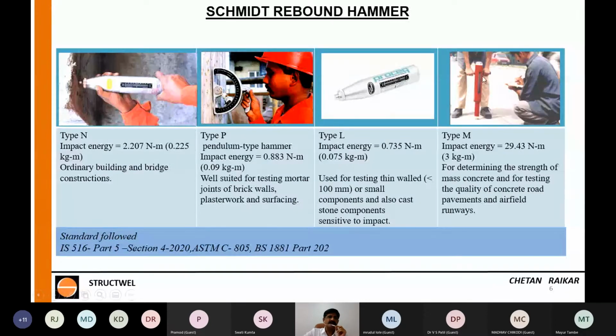This is Schmidt hammer. Schmidt hammer is of different types, you know, M type, that is medium, L is light, P is pendulum type, N is normal. This is generally used on ordinary buildings, bridges. This is well suited for testing mortars or plasters and surface renderings. This is meant for thin walls, you know, 100 mm or thinner walls, if you have to take 75 mm, because this has this N, P, L and M depends on the impact energy. You can see the impact energy is different for each of them.